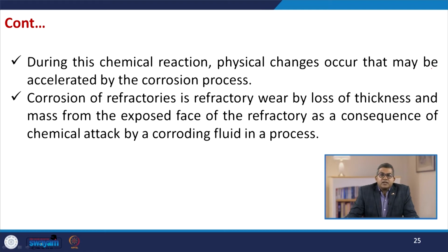Corrosion of refractories is the refractory wear by loss of thickness and mass from the exposed face of the refractory as a consequence of chemical attack by a corroding fluid in a process. Now, in this case, the refractory and corroding fluid react together, approaching chemical equilibrium in the zone of contact between the refractory and the fluid. The phase equilibrium diagram can be used to analyze the corrosion situation and to predict the chemical strategies to minimize the corrosion and wear rates.